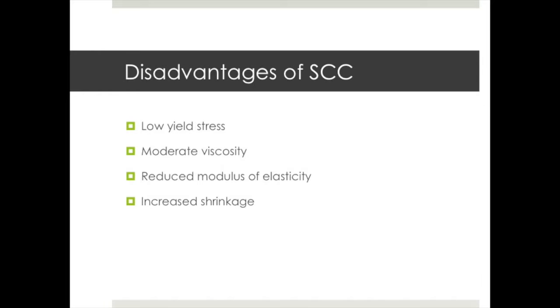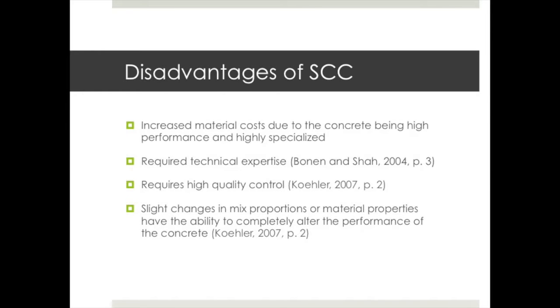Achieving deformability, stability, and low blockage, however, results in a low yield value, a moderate viscosity, a reduced modulus of elasticity, and increased shrinkage due to factors such as high paste volumes or low coarse aggregate contents. Other disadvantages of SCC include the increased material costs due to the concrete being high performance and highly specialized, and the required technical expertise of the concrete in its fresh and hardened states that are required in order to achieve high quality. Another disadvantage of using SCC presented by Kohler is that the SCC requires high quality control because slight changes in mixed proportions or material properties have the ability to completely alter the performance of the concrete.